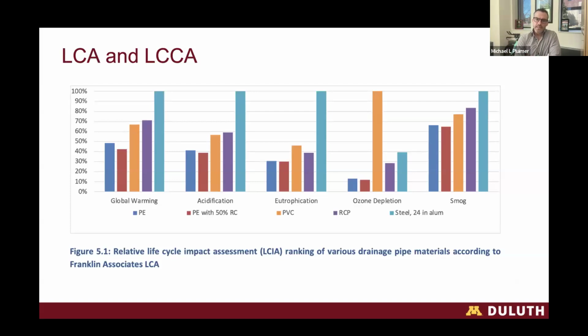Then we also did a literature review to do a life cycle analysis, to determine the potential environmental benefits of pipes manufactured with recycled content over other materials. So in this, we have 5 different categories that were evaluated by Franklin Associates. This is a published independent study that was done on different piping materials. And we're comparing polyethylene in the blue bar with polyethylene with 50% recycled content with the red bar, PVC with the orange, reinforced concrete pipe in the purple, and then steel, aluminized steel in the light blue.